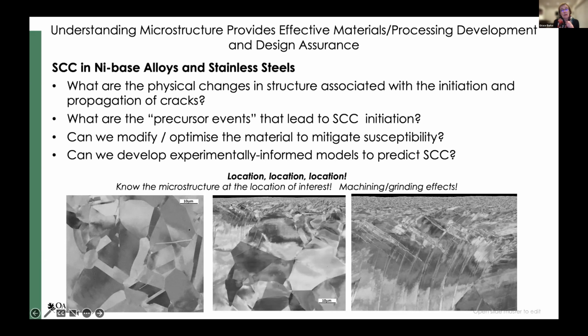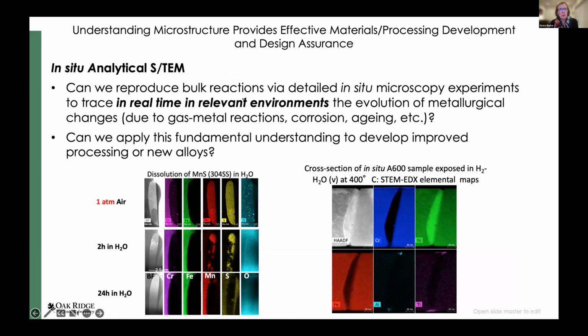However, these are metallographic cross sections prepared that go to the outer surface. So this is the region that is in contact with the environment. And you can see these are much more heavily deformed, with an ultra fine grained microstructure at the surface. So lots of deformation. So we're looking at two different things. Location is important to keep in mind. And when we generate our data on bulk reactions and bulk materials, can we apply any in situ characterization to this study to trace relevant reactions in real time? Can we see the evolution of those changes? And is that fundamental understanding then something we can apply to develop improved models or alloys?